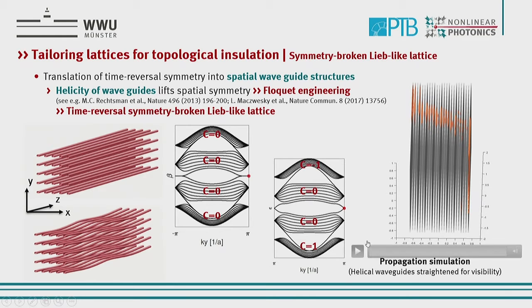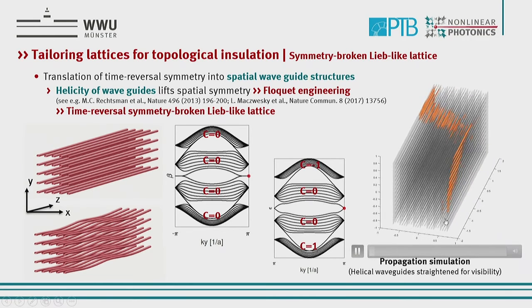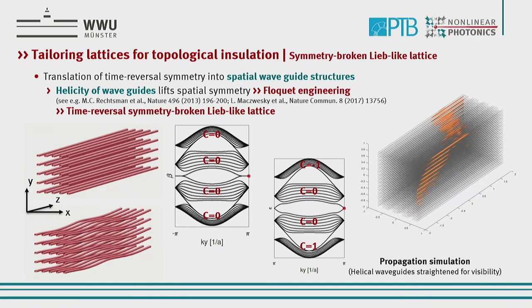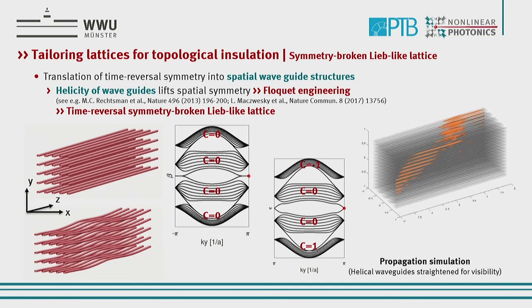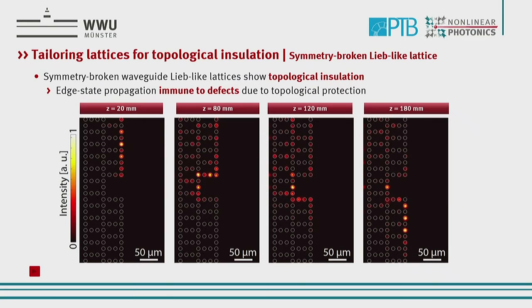And as you see here in the numerical simulation, in fact, in such a structure, we would have topological insulation. And then we can make a test if this is really true. This is a numerical simulation, and it shows very clearly we now have a propagation on the edge.